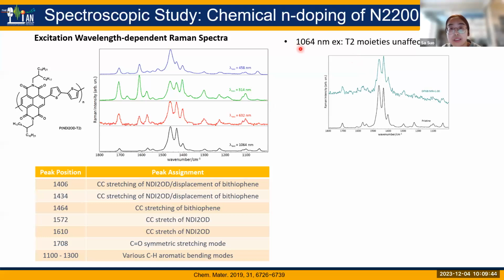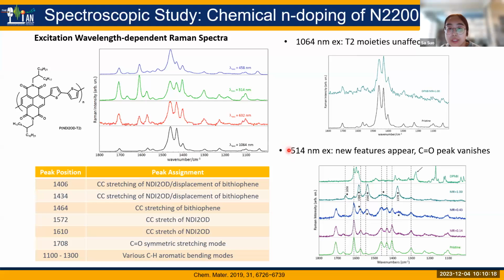So upon 1064 nanometer excitation, where they believe it is pre-resonance with the pi to pi star transition from the T2 unit, if we compare the undoped and doped spectra, we can see minimal feature change, and they believe it verifies the limited interaction between T2 and the localized polaron on the NDI unit. And then upon 514 nanometer excitation, where the polaron is actually resonant with these wavelengths, similar to what they observe in the IR spectra, they see new features appear, and also they see the CO and CC stretch vanish.